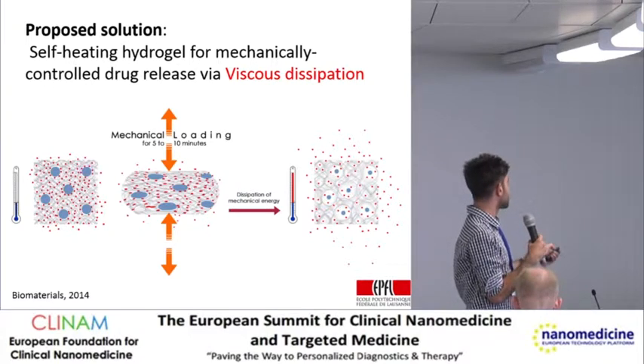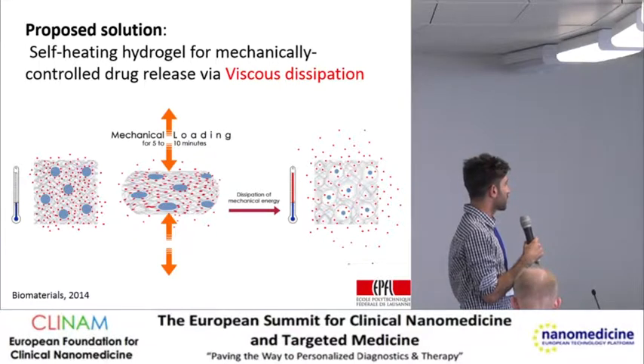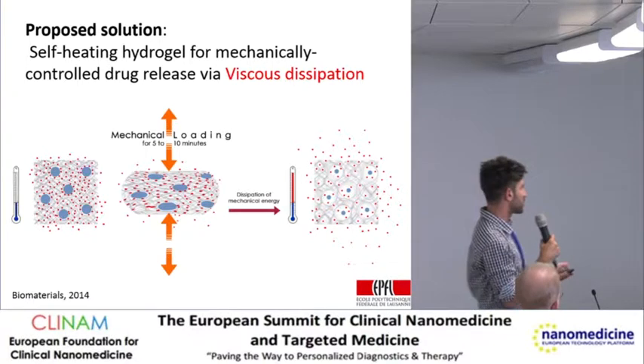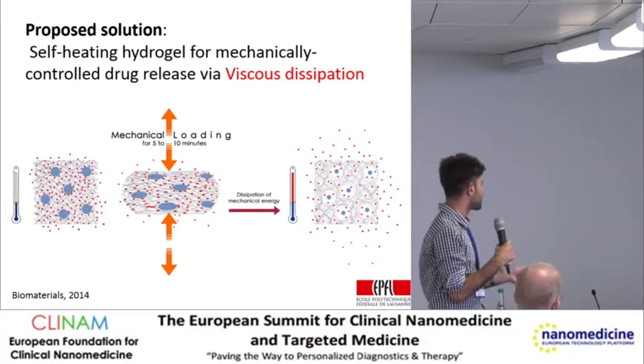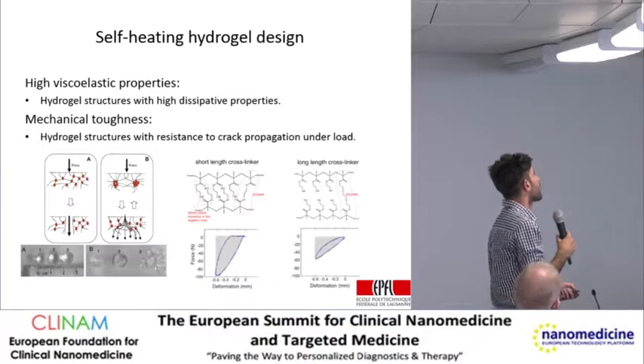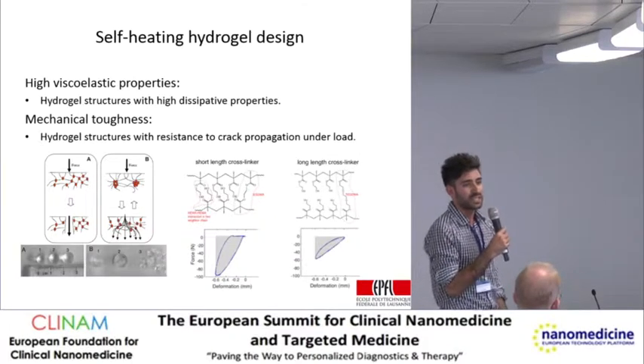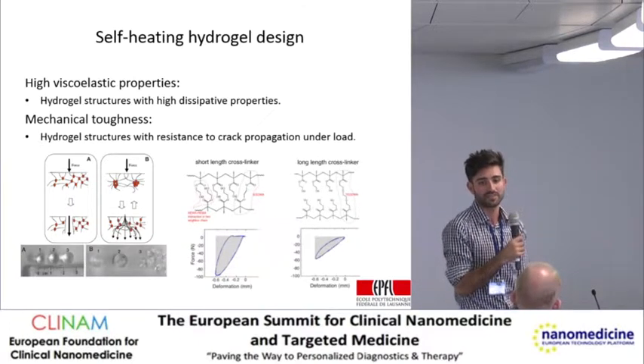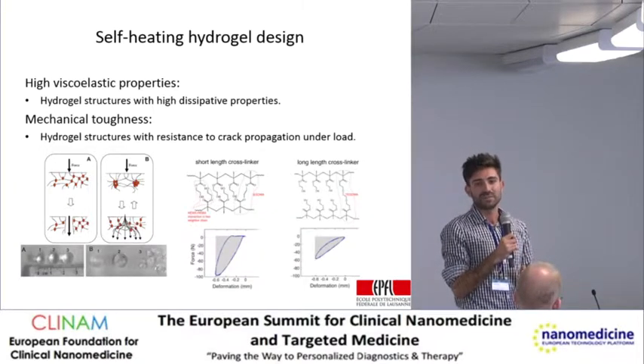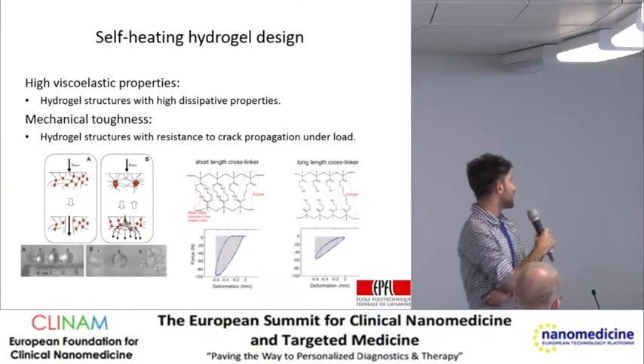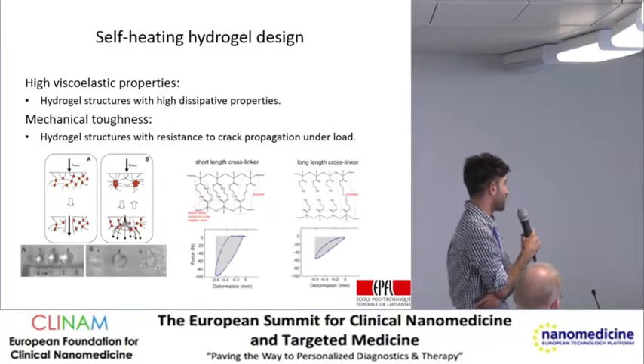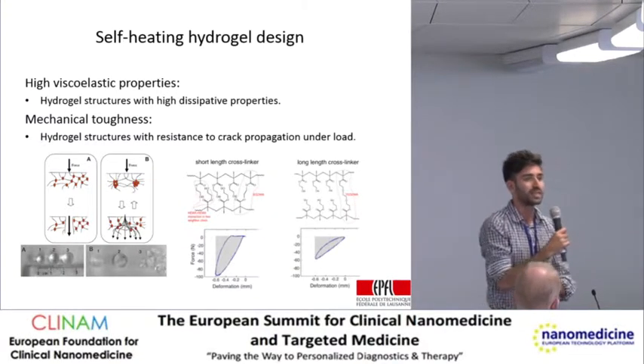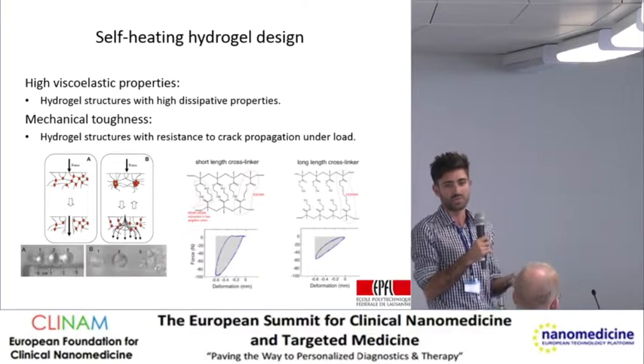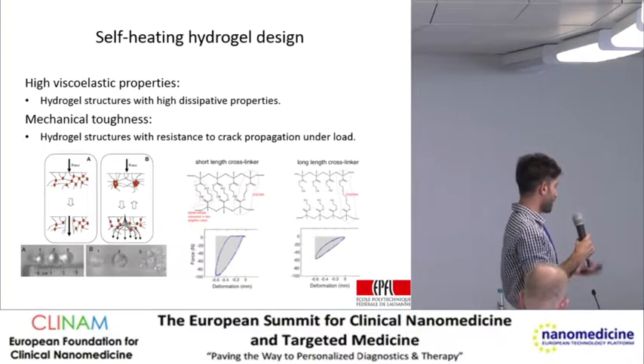So in this case, we control our release with mechanical load, but we provide a delay by playing with the viscoelasticity of this hydrogel, and then the drug can be released. Designing such a system with a hydrogel is very challenging. As you know, hydrogels are very soft materials with very poor mechanical properties. So what we need is a hydrogel with high dissipative properties and high mechanical toughness, meaning that in load-bearing applications, they shouldn't be ruined when you use them.